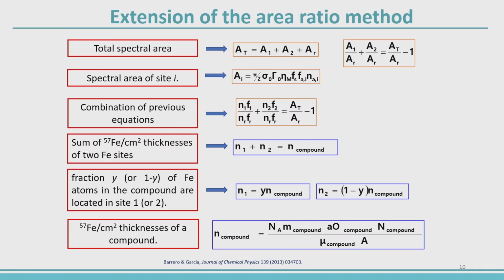Then, if we know or we guess the number of cations distributed in both sites, then we can use this simple formula. We replace here. Another thing that we assume is that all available crystallographic iron sites are occupied, so we assume here that O is equal to 1. Here we have the Avogadro number, the mass of the compound, the abundance of the iron, this is the number of iron ions in the compound, and this is the molecular weight of the compound, and this is the area of the absorber.